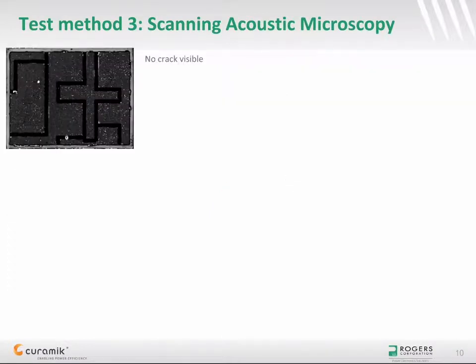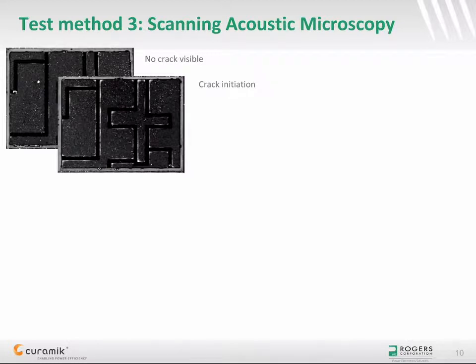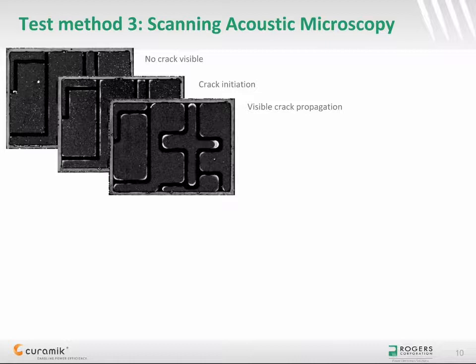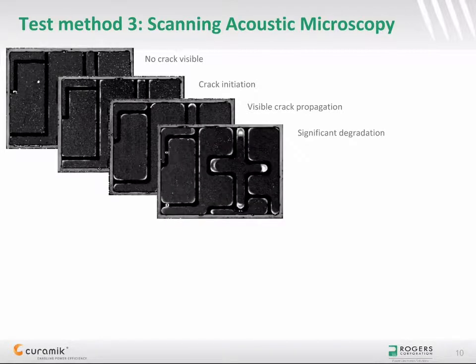Scanning acoustic microscopy is a well-known non-destructive test method for failure analysis. It employs ultrasound to penetrate solid materials and make visible images of defects such as cracks, delamination, and voids. This investigation process is repeated in a systematic pattern until the entire region of interest has been scanned. As a result, an image of the substrate is generated. The contrast on the image highlights the location of a defect. At time 0, we don't see any defect. But after some temperature cycles, the change in contrast indicates that the formation of cracks has started and that the cracks are propagating until a significant degradation is achieved.